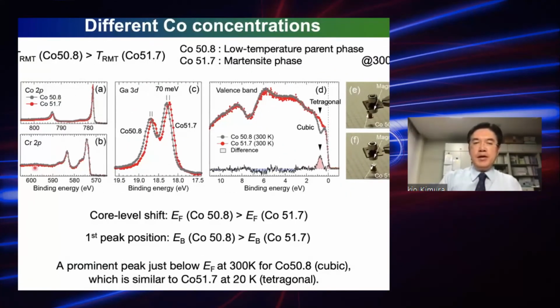So now we compare the difference of the cobalt concentrations. As I mentioned, the cobalt-poor sample has a higher transition temperature compared to the cobalt-rich samples. From the core level photoemission, you see some core level shift by 70 meV. The cobalt-rich sample has a lower binding energy peak, while the cobalt-poor sample has a higher binding energy peak. This suggests that the Fermi energy position for the cobalt-poor sample is higher than that of the cobalt-rich samples.